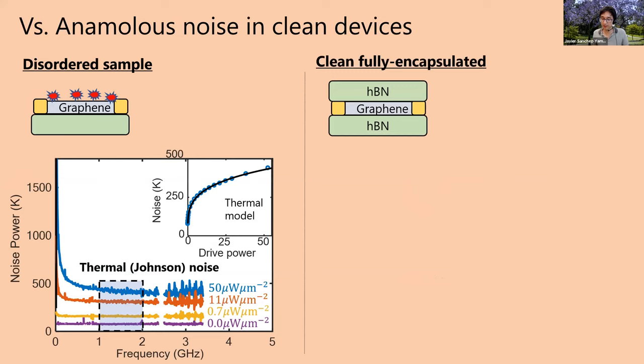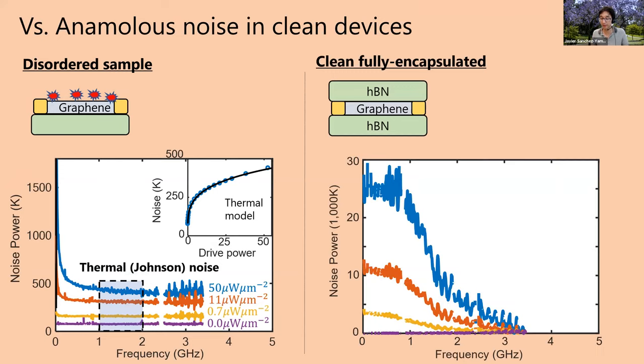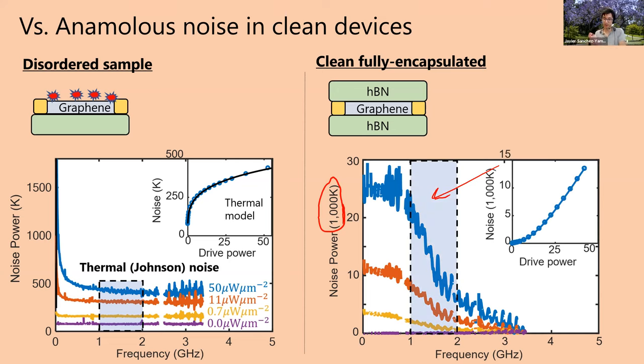Then when we measured a clean device, we saw that it was very noisy, and we can look at the frequency spectrum of the noise. It's extremely noisy. We're getting noise powers that are not measured in hundreds of Kelvin, but in thousands of Kelvin. Also, it's larger at small frequencies than at large frequencies, so there's a very clear frequency dependence to the noise. That was pretty odd. So, a very noisy sample that's clean and is noisy at low frequencies.